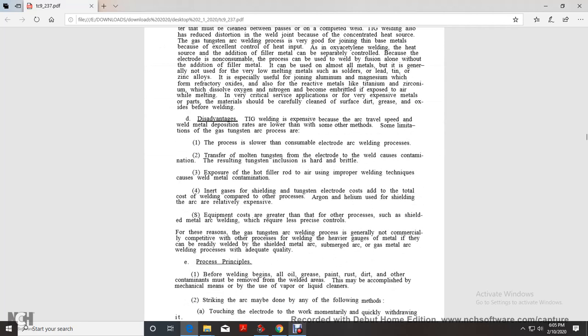Alright, the disadvantages. TIG welding is expensive because the arc travel speed and the weld metal deposit rate are lower than some other methods. The gas tungsten arc process is slower than consumable arc welding processes. Contact of the molten filler metal with the electrode can cause contamination, resulting in tungsten inclusions that are hard and brittle, as does exposing the hot filler rod to air, or using improper welding technique for the metal combination.